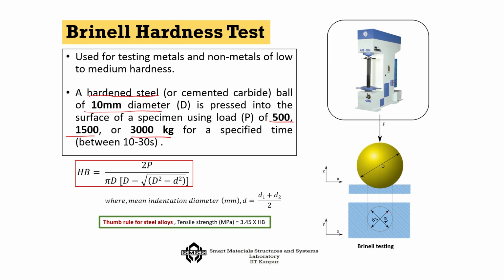So, we look into these indentation patterns, and we find out the minimum and the maximum diameter through different measurements at different points, and then we take the average indentation diameter. The average indentation diameter is known, the ball diameter is already known, the load is known, so we should be able to calculate HB. Very interestingly, here also there is a thumb rule that for steel alloys the tensile strength is about 3.45 times HB, but this is just an empirical thumb rule.